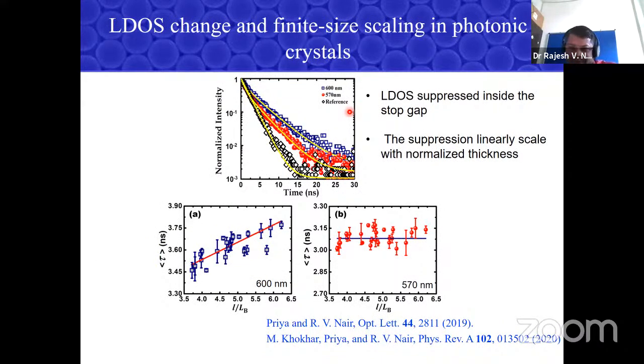Those who are specifically interested in more about it, we have written a follow-up detailed article in Physical Review about how we can understand the spontaneous emission systems. So at the band gap, it shows scaling, and outside the gap, it does not show any scaling. Okay, and this scaling is not arbitrary. It does depend on the normalized thickness of the sample.